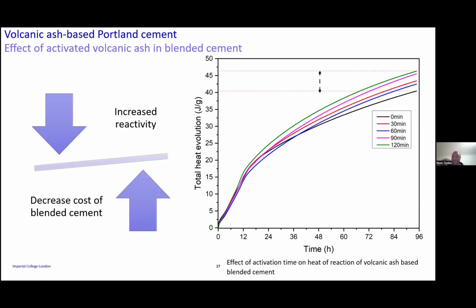So with the volcanic ash that has been activated for different times, we can see an increase in the heat of the reaction. Here, I mixed Portland cement with 25% of volcanic ash, for the same milling time, and one can see how the heat is increasing. The increase of the heat, what does it mean? It means that